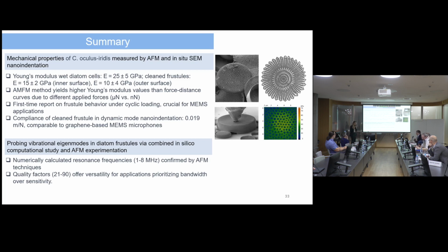We performed for the first time dynamic cyclic loading of a diatom frustule under the indenter in a scanning electron microscope, which is indeed important for MEMS applications. The calculated compliance in the range of 0.019 meters per Newton is comparable to graphene-based MEMS microphones. We also calculated numerically resonance frequencies of diatoms, which are in the range from 1 to 8 megahertz, and these results were confirmed for the first time using atomic force microscopy. Quality factors in the range from 20 to 90 offer some versatility for applications that prioritize bandwidth over sensitivity.